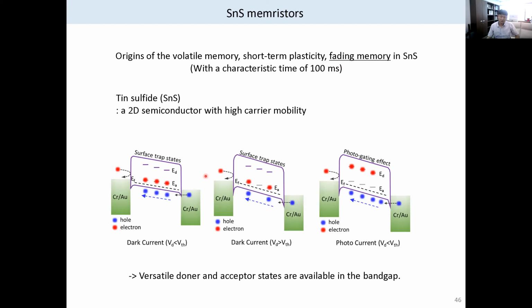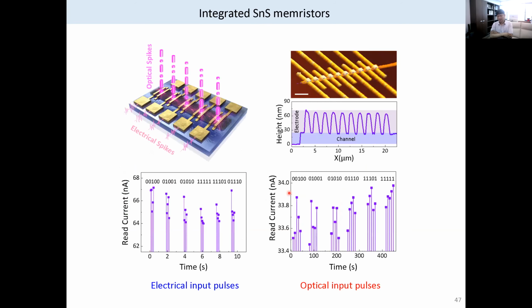And what happens? This is our interpretation. We have this ambipolar semiconductor with acceptor states and donor states. By electric pulse, we make less p-type doping, and by optical pulses, we have more p-type doping. So we suggested this band diagram, but we have limited proof of it. But anyway, our experiments say that we have both conductivity decrease and conductivity increase by different kinds of stimulation.